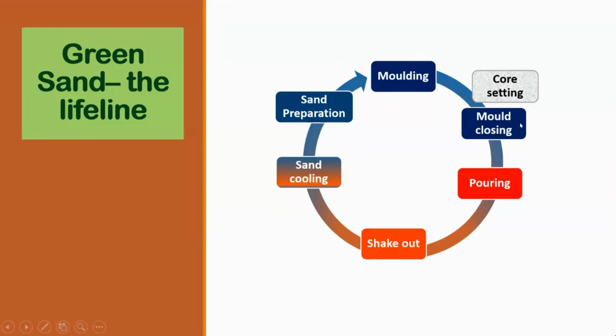You have the molds ready for pouring. So you pour the molds and then the castings come out by shaking out the molds. And when the castings are taken out, the sand is taken to the sand cooling area where it is cooled down. And then you prepare it again for the molding purpose. And then you make the mold, set the cores inside, and then close it again. So the whole cycle, it represents the path the system sand travels.